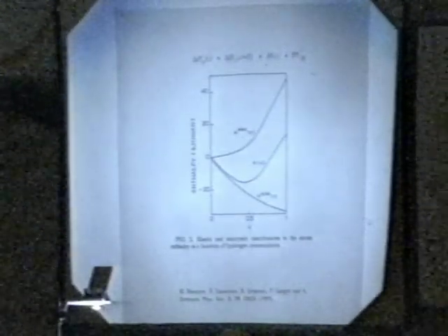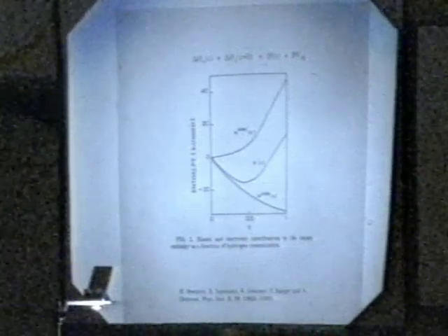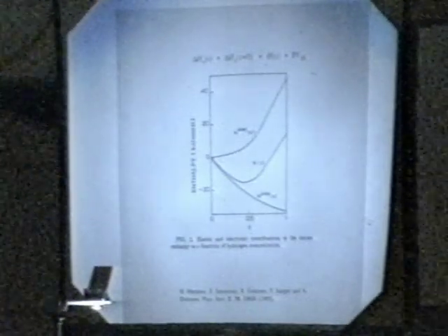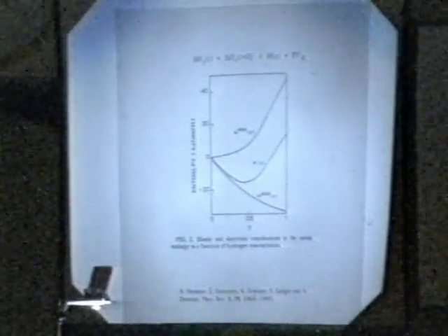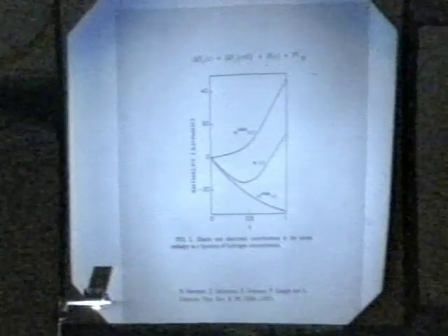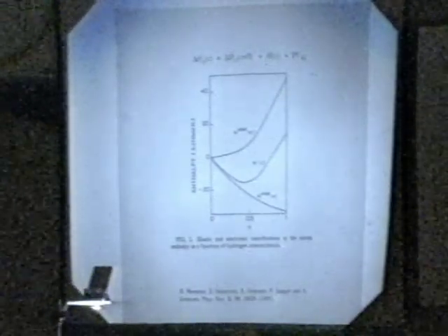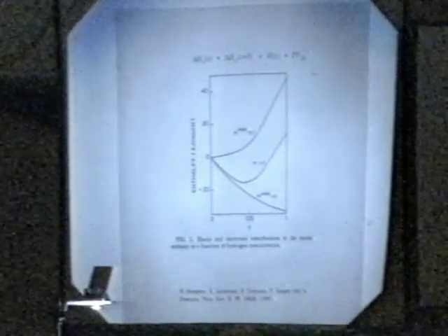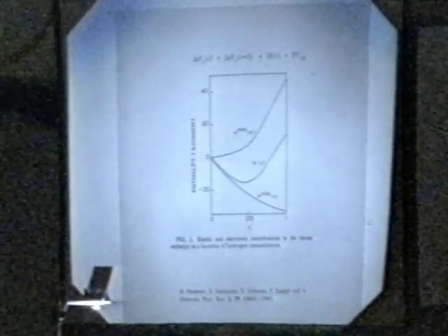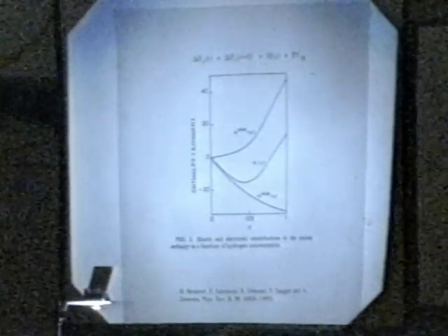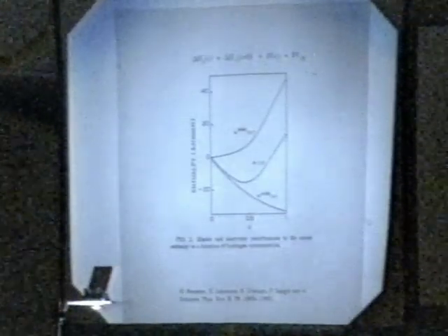Here's our unfavourable electronic term, interpreted conventionally as a relatively penalty-free occupation of the high density of states 4d band in the palladium lattice, followed by a high penalty occupation of the low density of states in the 5s band by the electron that is donated to the lattice from the hydrogen atom. So we add these two functions together, we get this function for the partial molar enthalpy. In other words, an initial decrease as the elastic term dominates, followed by a rise to eventually endothermic values as the electronic term dominates. The chemical potential, as Juliana Cabrera showed yesterday, does more or less the same thing, but it's, again, susceptible to the same decompositions. Okay. Now this is very much an idealized view.